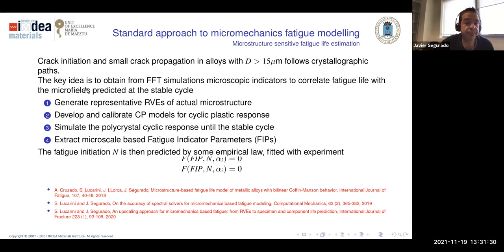And when we have this, the fourth step is to post-process the result to get some fatigue indicator parameters. So the aim is then finding a very simple phenomenological law that, if I have these fatigue indicator parameters, when the law is fit, is able to give me the number of cycles that this will survive. So the larger the FIP, the smaller the number of cycles.